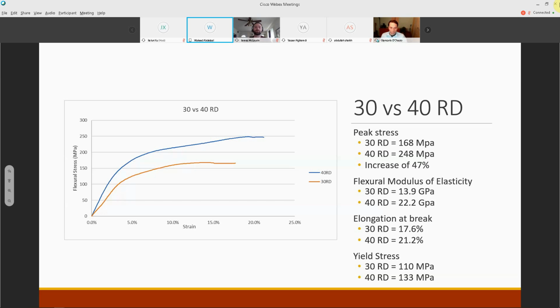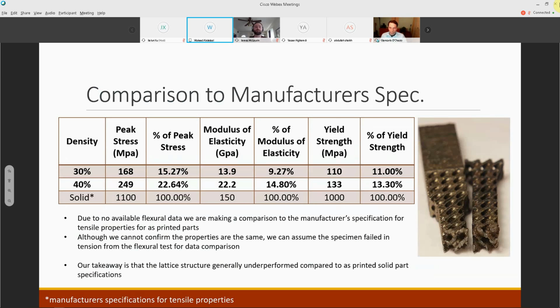The yield strength shows that for the 30% it is 110 megapascals, and for the 40% it equals 133 megapascals. Again, here we are comparing the 2 different densities. This time we're adding information on the solid density, the data from the manufacturer specs on the material that we shared in the previous slide on mechanical properties. Due to no available flexural data, we are comparing to the manufacturer's specifications for tensile properties for as-printed parts. Although we cannot confirm the properties are the same, we assume the specimen failed in tension from the flexural test for data comparison.